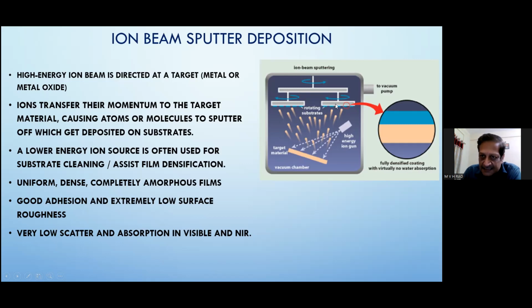deposited. And in this case, it itself gives a very good film as it is, as good as ion assist. But to further improve the process, sometimes another ion source is used as an assist, to have very smooth films with very low micro roughness, so that the interface is very well defined. But generally, only in special applications you require one more assist gun. Then two ion sources will be there. One for etching the target, removing the material, and the other for assist.